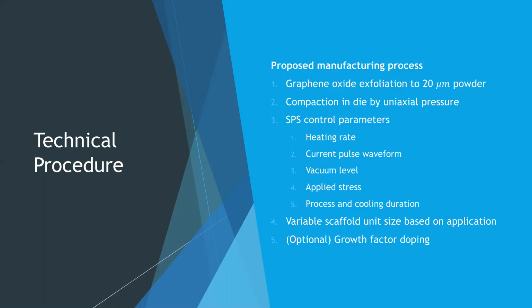With the die ready, the sample will be placed inside the spark plasma sintering machine, and the machine will be set to operate at a heating rate of 75 Celsius per minute, a nominal applied stress of 50 megapascal, and a final temperature of 300 Celsius. Once cool, remove the samples from the die and prepare for packaging.